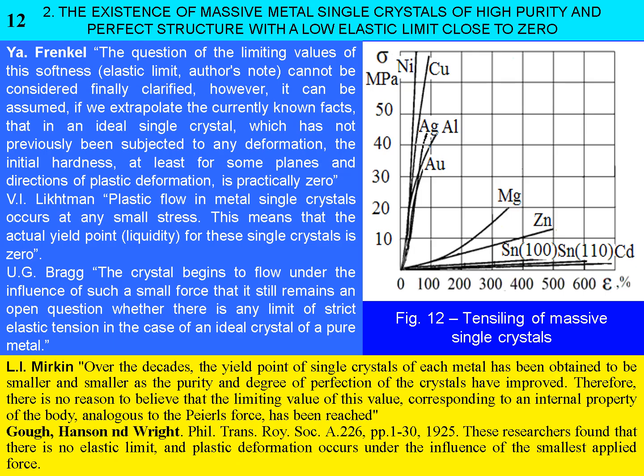According to the predicted trend, a further increase in crystal size should reduce the yield stress to near zero. This is confirmed by artificially grown, massive, high-purity single crystals with nearly perfect structures (Slide 12). These crystals exhibit extremely low yield stress, approaching zero, which provides direct evidence of lattice instability. This conclusion is supported by statements from leading researchers. One such statement reads: Plastic flow in metallic single crystals begins at any small stress.